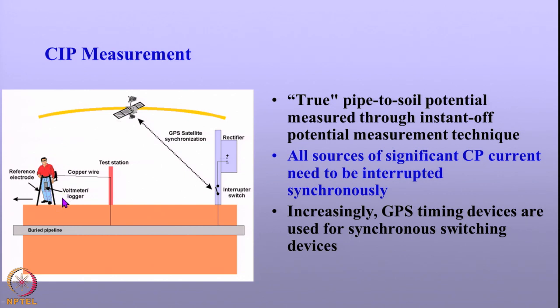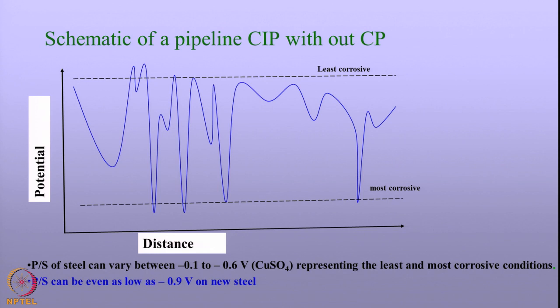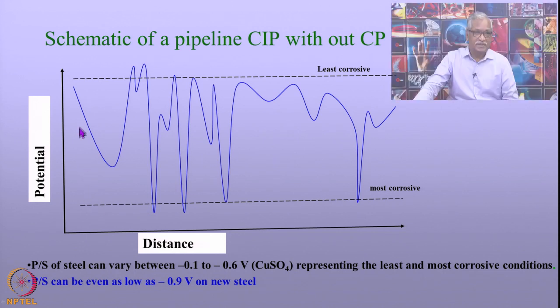It is very important that in the instant off technique, we synchronize all the devices, all the CP current providing stations, so that the pipeline does not receive current. This synchronization can be done using GPS satellite synchronization, so that the pipeline does not receive current when it is interrupted. What is given is a schematic of pipeline close interval potential measurements without CP, without cathodic protection. As you see here, the potential fluctuates quite significantly, it is not as smooth.